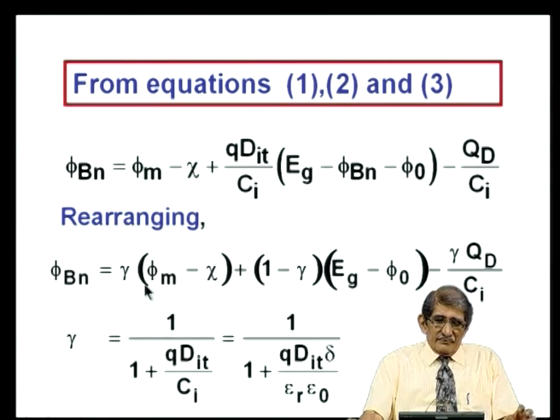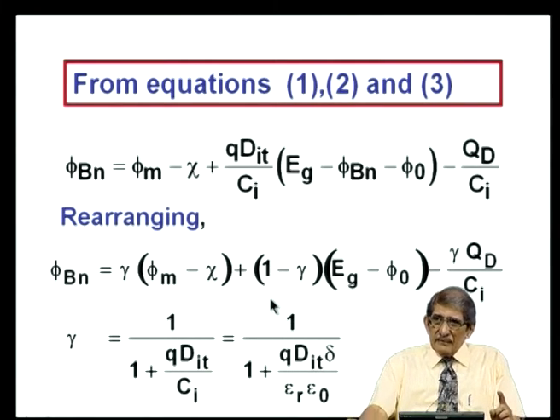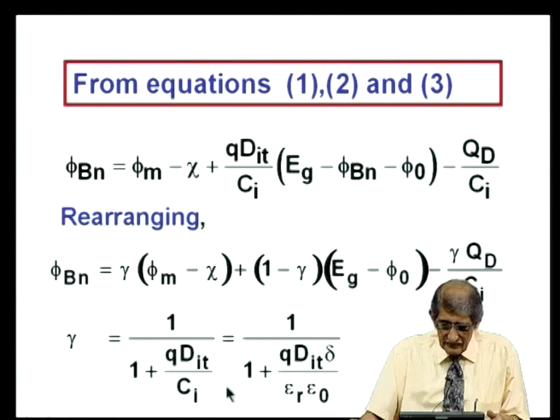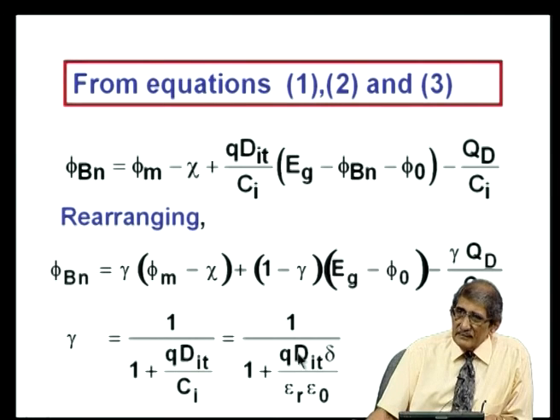So, now you can see, if gamma is equal to 0, when will gamma be equal to 0? When D I t is very large. When D I t is very large, infinity, gamma will be equal to 0. So, gamma equal to 0 means this term is equal to 1 and this is equal to 0. So, when the DIT is very, very large, phi b n is equal to E g minus phi naught, independent of phi m. That supports the equation that we have written there, that this gamma is related to delta and DIT. C I is that one. So, it depends upon delta and DIT. If delta is 0, of course, you would not get anything.